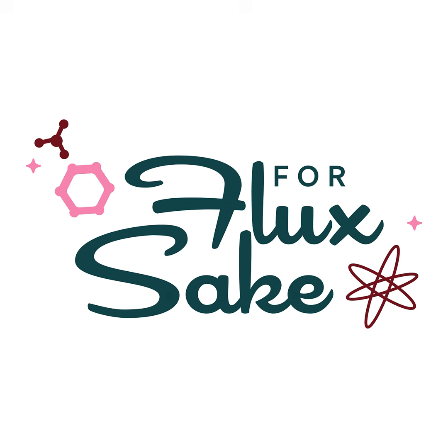Because although everybody assumes, oh, you layer them together, they just melt together. Nope, those two layers are independent chemistries, even when you fire them, because our melting process, once again, I say this all the time on the main show, it is insanely short. Our glazes only melt for the last 100 degrees C, 180 degrees F of the firing on the way up, and they only remain viscous until about 850 C on the way down, and that's about an hour. So the total melting process in any firing is about 2 hours at most.